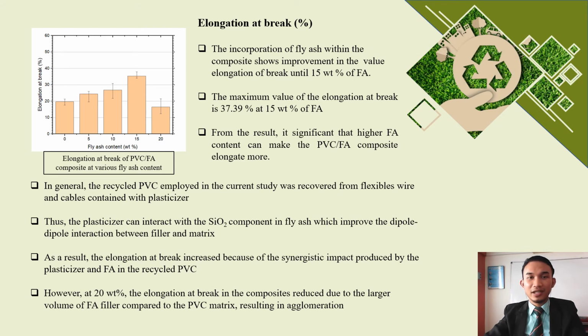In general, the recycled PVC employed in the current study was recovered from flexible wire and cable containing plasticizer. Thus, the plasticizer can interact with the silica component in fly ash, which improves the dipole-dipole interaction between filler and matrix. As a result, the elongation at break increased because of the synergistic impact produced by the plasticizer and the fly ash in the recycled PVC. However, at 20 weight percentage, the elongation at break in the composite reduced due to the larger volume of fly ash filler compared to the PVC matrix, resulting in agglomeration.